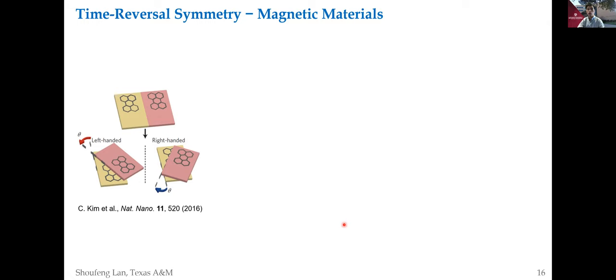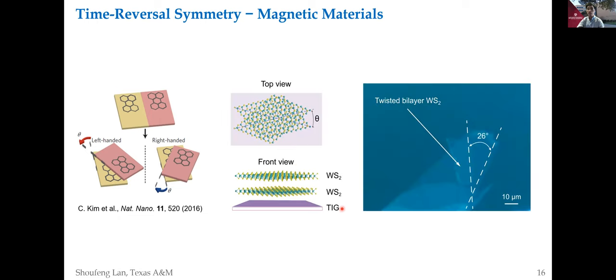And they suggest that this optical rotation can be further enhanced by using semiconducting 2D materials with excitons. That is why we use WS2, or tungsten disulfide, because WS2 is a semiconducting 2D material which also has excitons. And to couple to the magnetism, we also place the twisted layers on top of a ferromagnetic substrate. In this case, the ferromagnetic substrate is thulium iron garnet, or TIG. The TIG has a Curie temperature of around 400 Kelvin, which is above room temperature, so we can operate this device at room temperature. And also the ferromagnetism of the TIG is relatively soft, so we can easily switch the direction of the magnetic moment of the ferromagnetic substrate.